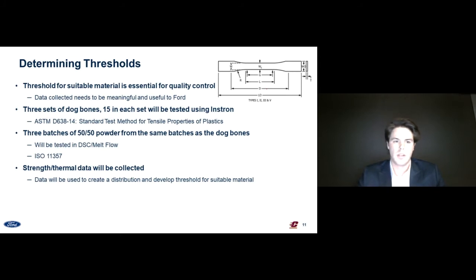Those dog bones will be tested using the Instron machine following the ASTM standard test method for tensile properties of plastics. And from those same 3 batches, we'll be getting powder, a 50-50 mix of virgin and used powder, to test in the DSC machine. We'll be following the ISO standard for DSC testing of plastics. From these tests, we'll be gathering mechanical and thermal data that will be used to create a statistical distribution and develop a threshold for a quality material and product.